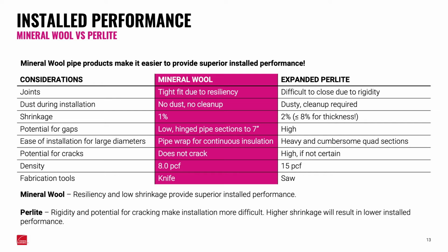Something with expanded perlite, it generally has a requirement of 2%, but it allows up to 8% shrinkage in thickness, and that can be substantial if you're talking about thermal performance. So there's a potential to underspec things, particularly if you have a lower density or an out of spec product. The potential for gaps with mineral wool, there's hinge sections up to 7 inches, so that means that there's only one longitudinal joint on that system using that size. Going above that, you're only going to have 2 longitudinal joints as you do that.